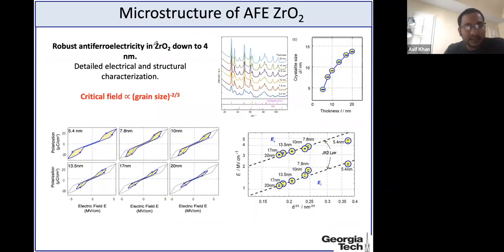Okay, so the first thing that we did is we wanted to correlate the microstructure with the electrical characteristics. One of my students, Nujat Tasneem, found a very interesting result: if you look at antiferroelectrics and scale them down, then the critical field for these phase transitions depends on the grain size raised to power negative 2/3. For example, here the critical fields are a linear function of d to the power negative 2/3. So that tells us that not only is it a challenge, but the microstructure actually controls a lot of things within the material itself, including the electrical functional responses. That was one of the interesting findings that we had in our group early on.